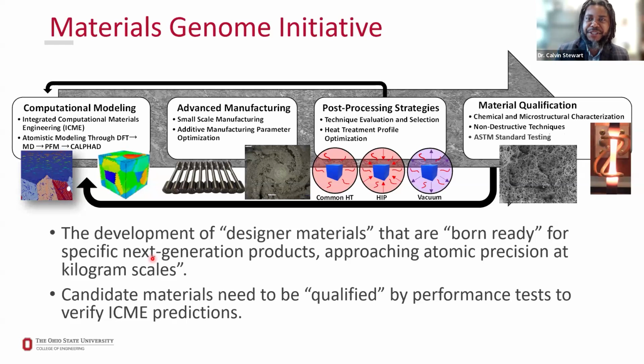from chemistry, we can predict structure. From structure, we can predict properties. And from those properties, arrive at performance in extreme environments. But there's a lot of steps in this materials genome initiative that we have to step through, from the computational, from basic computational thermodynamics and molecular dynamics, to then making the material, from using additive or small scale arc melting to create small samples, to then post-processing, thermomechanically processing materials to arrive at a good structure, to then testing and qualifying the performance of those materials and components.